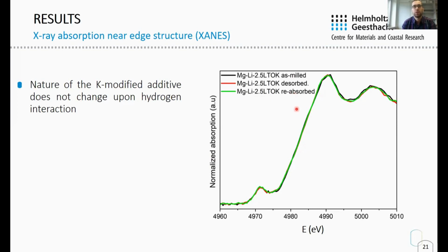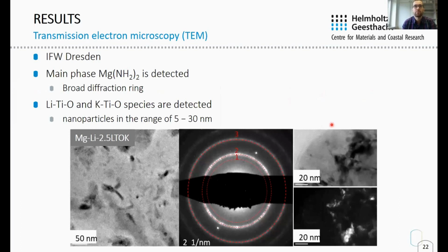In order to determine the nature of the additive based on the knowledge I have so far, I did transmission electron microscope observations of the as-milled samples. TEM observations were carried out in Dresden. A bright field image of the sample with potassium is shown on the left, and diffraction rings in the middle; the rings are related to the main phase, magnesium amide. And in this sample, nanoparticles of lithium titanium oxide and potassium titanium oxide were detected with sizes between 5 and 30 nanometers, which can be seen in the dark field image.